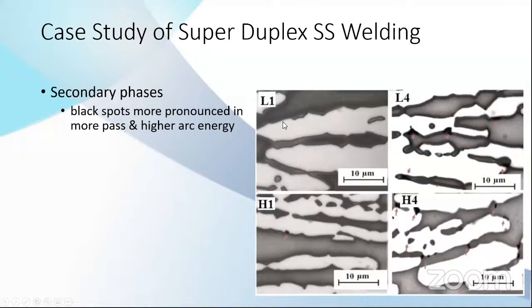Low heat input and only 1 pass, you have no secondary phase precipitation, no unwanted phase. But even with low heat input, if you have a lot of welding passes, you can see some black spots. When you have high heat input but only 1 pass, you have very minimal black spots. But high heat input and a lot of welding passes, you have many more secondary precipitation. So heat input is very important in a sensitive material like duplex.